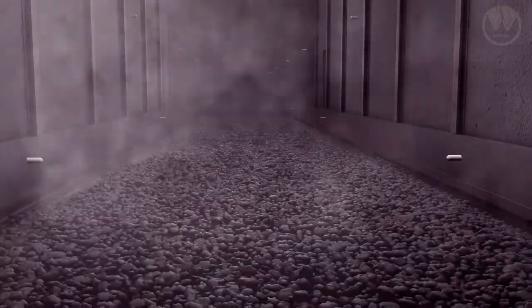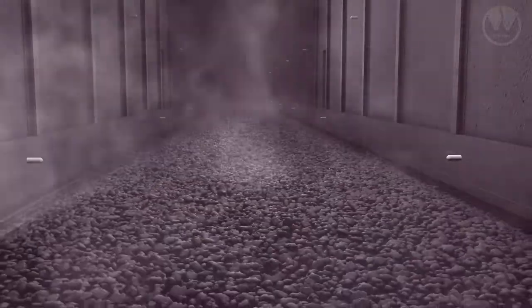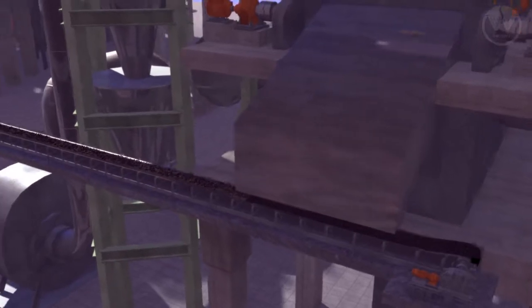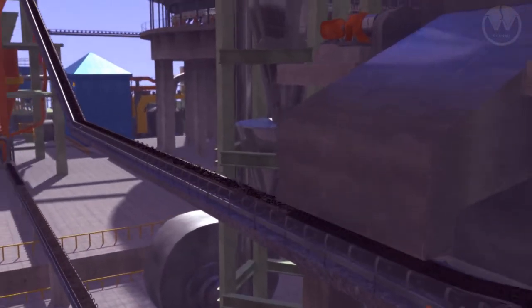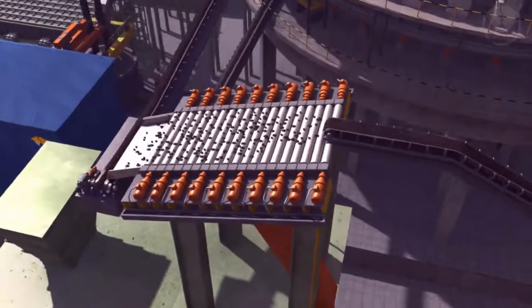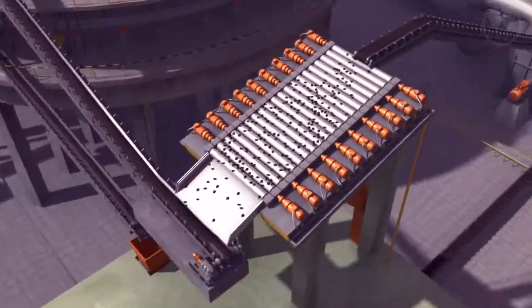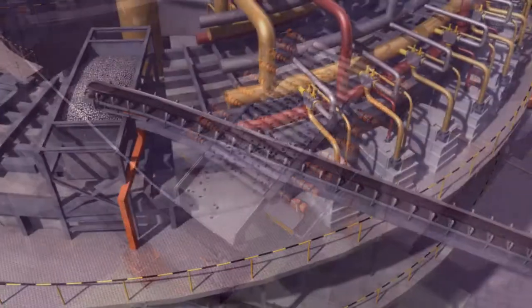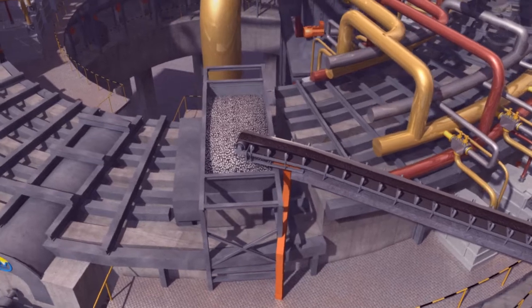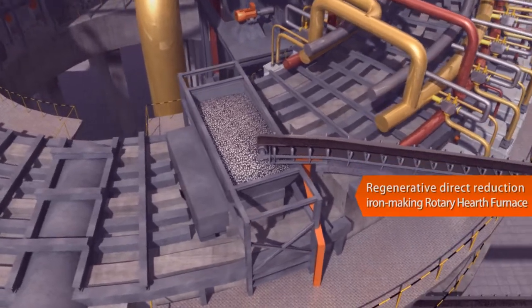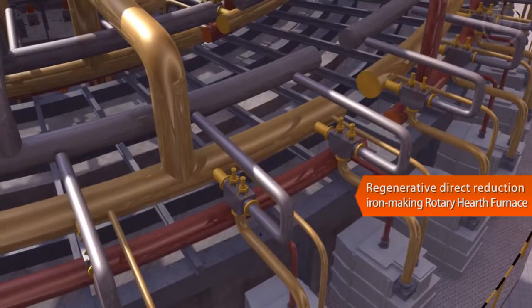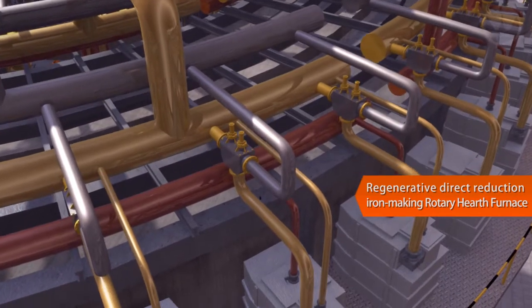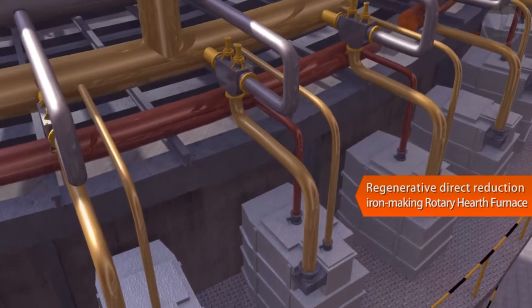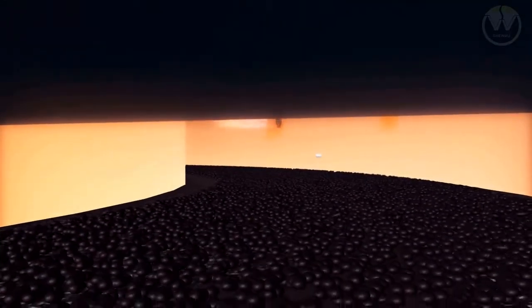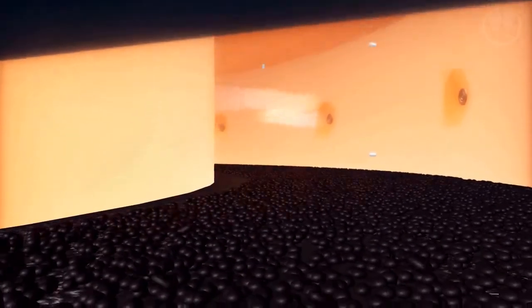Dried pellets from the dryer are sent to the screening system via belt conveyor. After that, the qualified dried pellets enter into Shenwu's regenerative direct reduction iron-making rotary hearth furnace. The carbonaceous pellets are uniformly distributed on the furnace hearth via the material distributing device. Inside the RHF, the wall, roof and burners are kept stationary, while the hearth rotates, driven by the hearth mechanism.